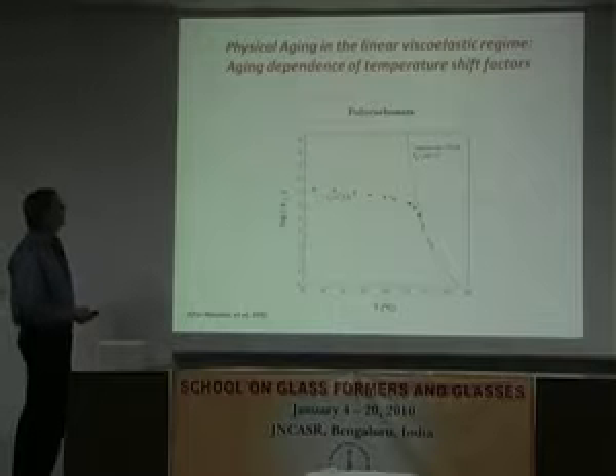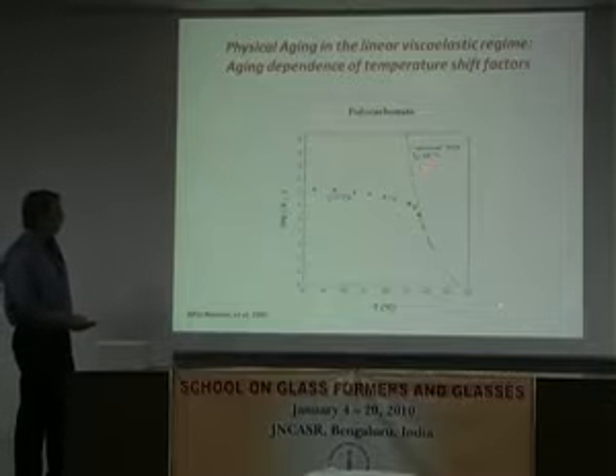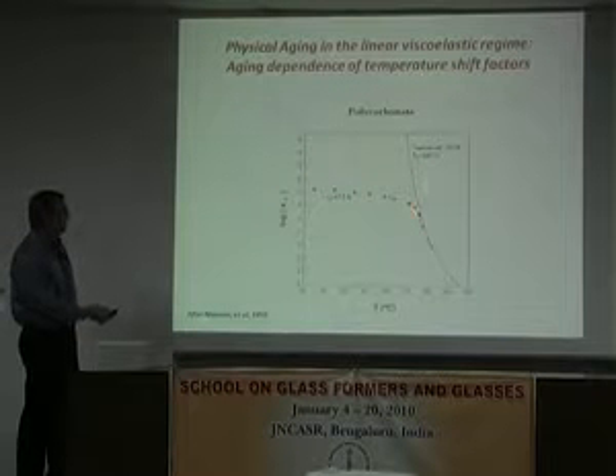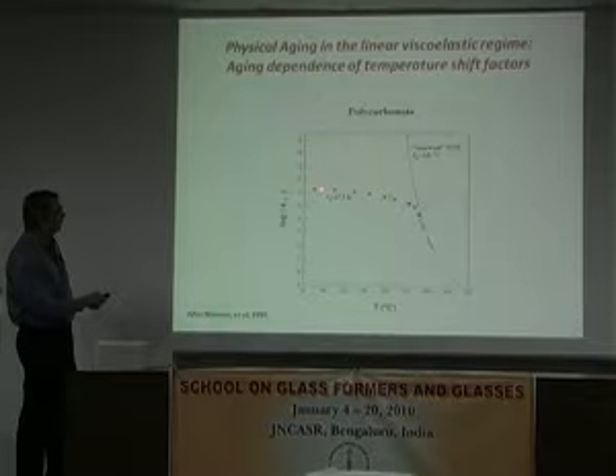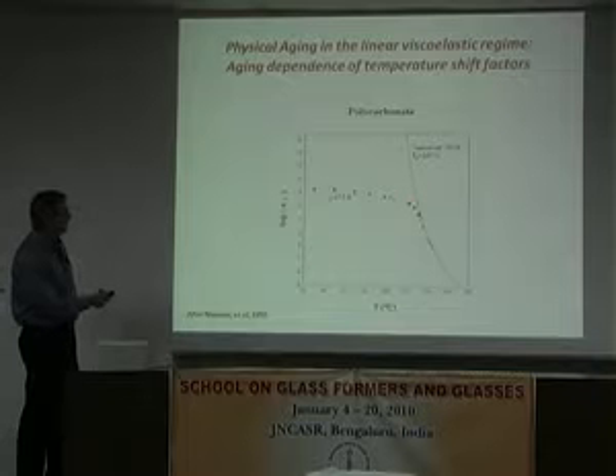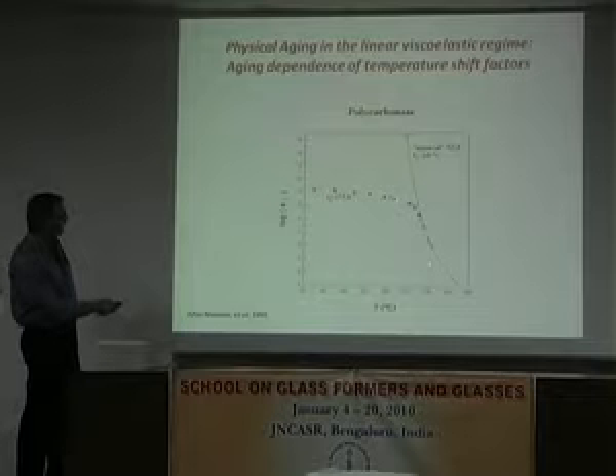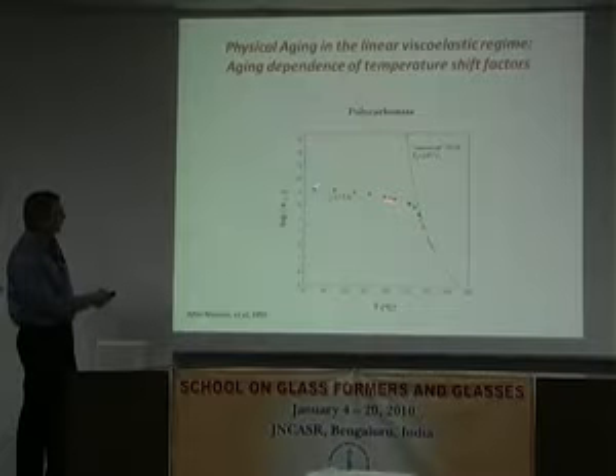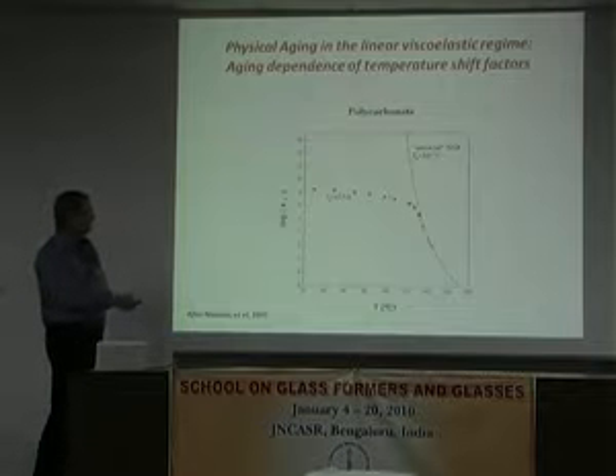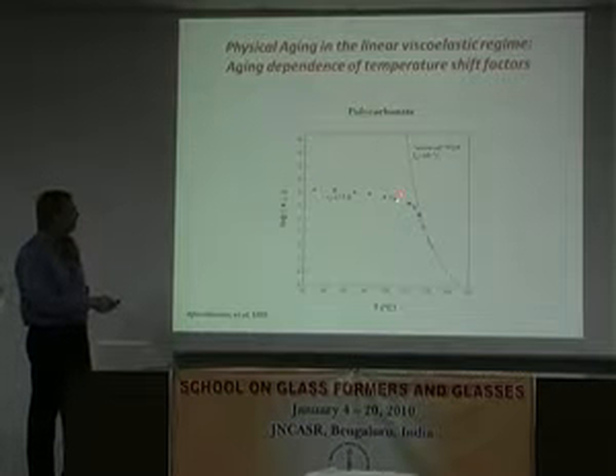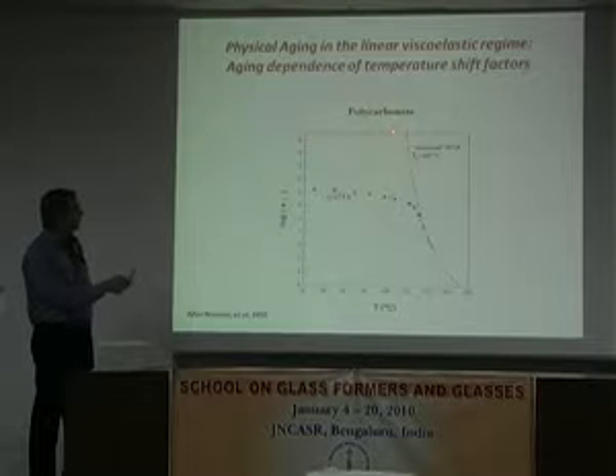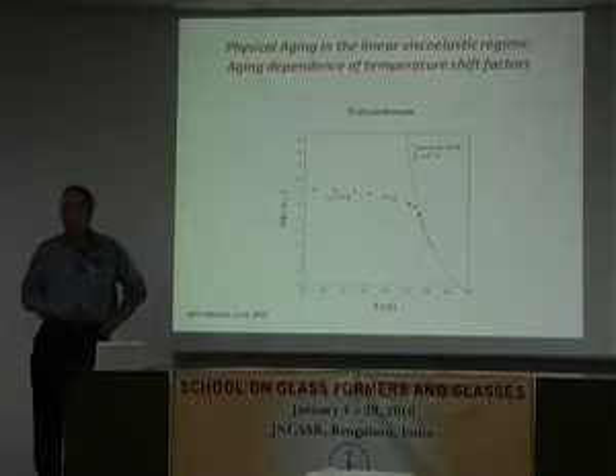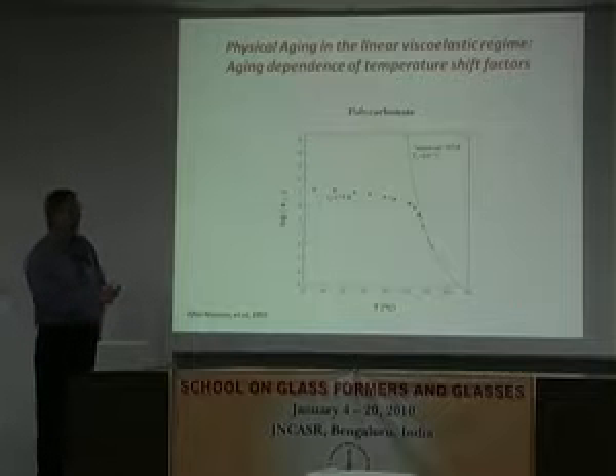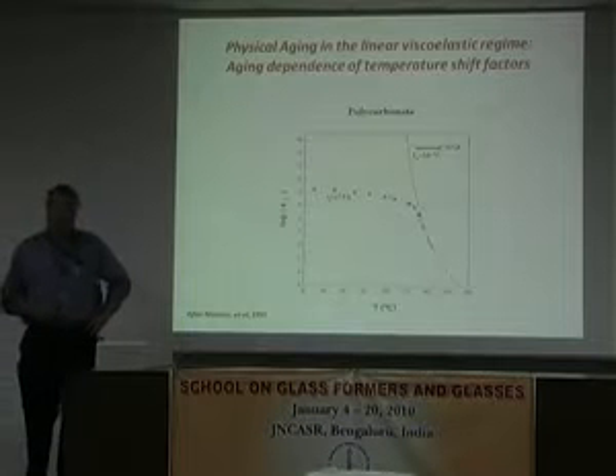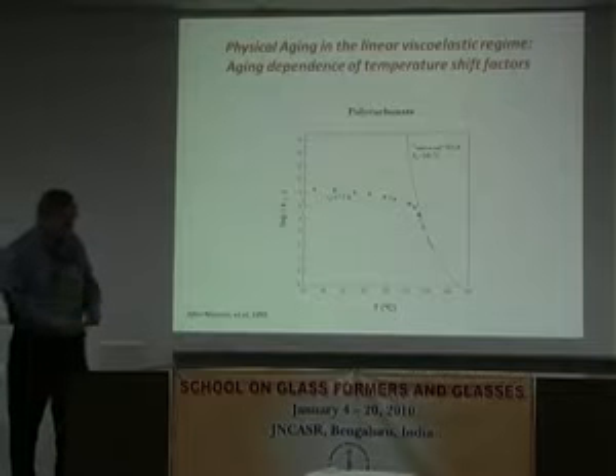And this just shows what it might look like. This is for polycarbonate. This would be the WLF response of the polycarbonate. And what we see is, because the material fell out of equilibrium, in this case, at 17.5 hours of aging time, it comes like this and deviates. And one of the challenges is ultimately what people want to know is, does this really go up, if I wait long enough, to the extrapolation of the WLF or Vogel-Fulcher behavior? And I'll come back to that in a moment.